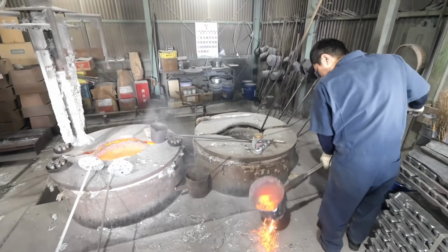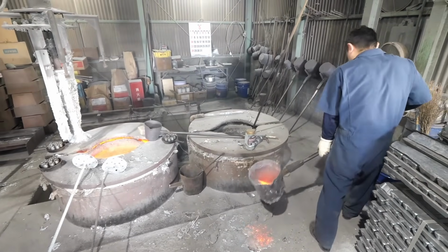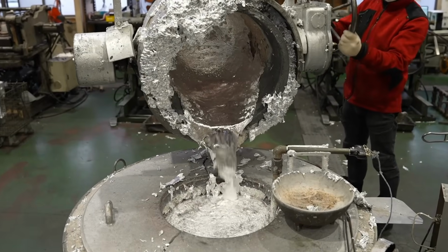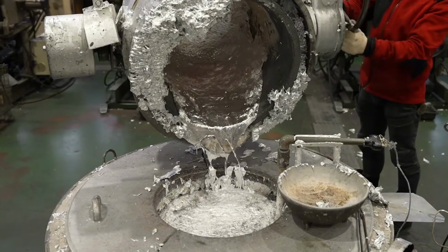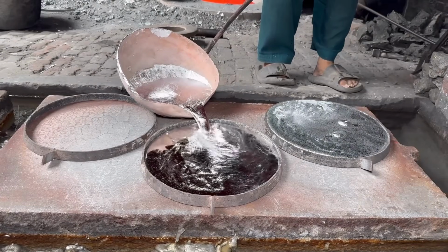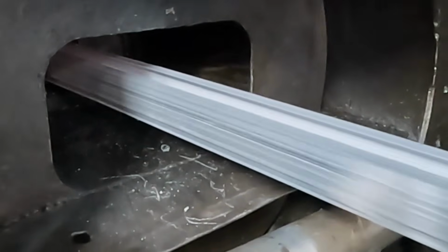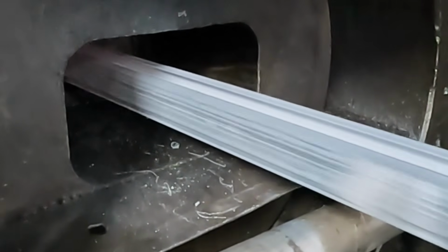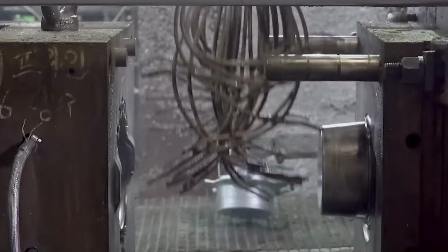Here's something most people don't realize. It takes about 2 pounds of aluminum oxide to produce 1 pound of aluminum. The oxygen doesn't vanish. It combines with the carbon anodes, which slowly burn away and must be replaced every few weeks. A single pot line can consume hundreds of carbon anodes per year.